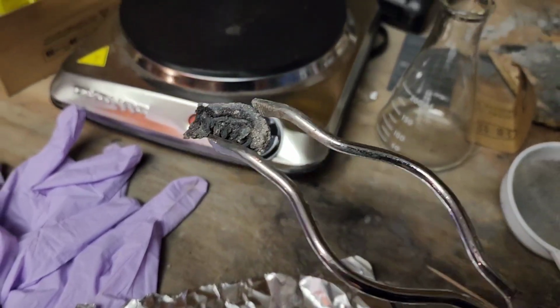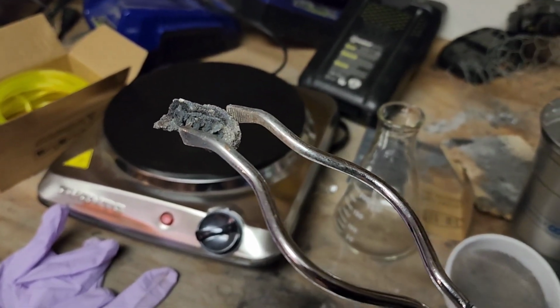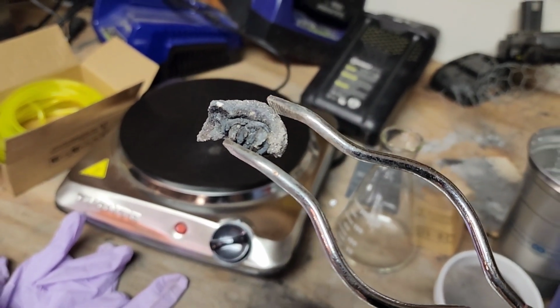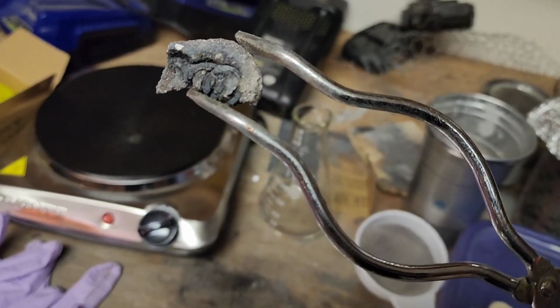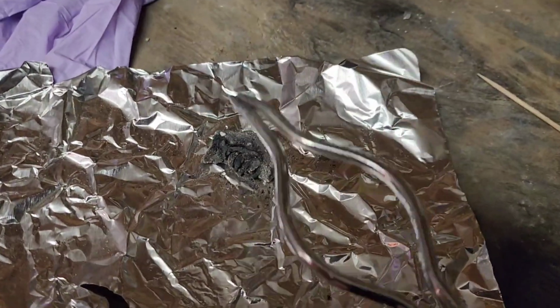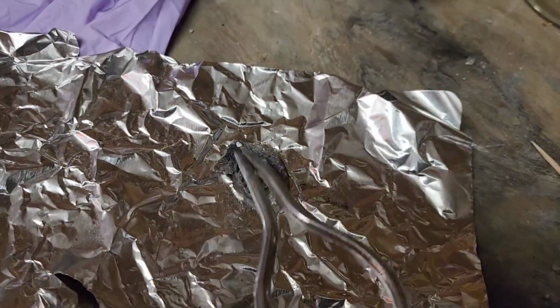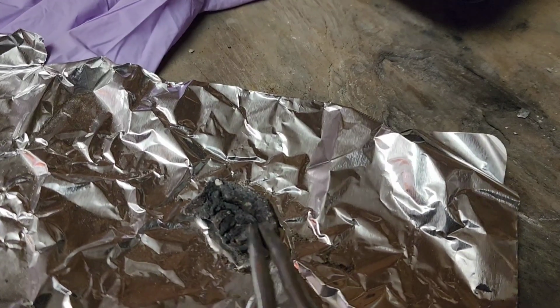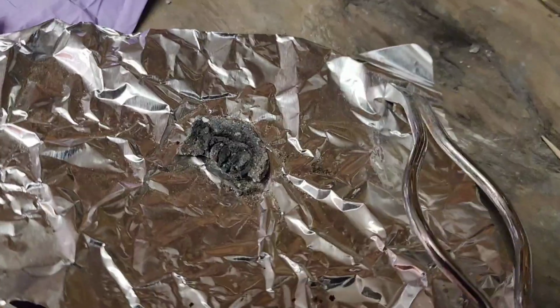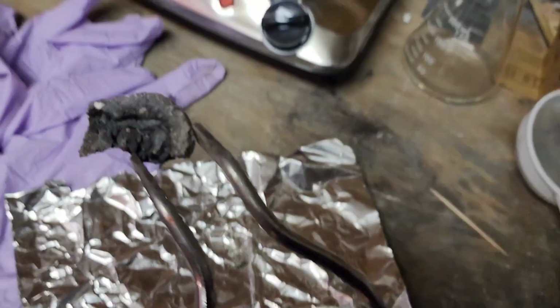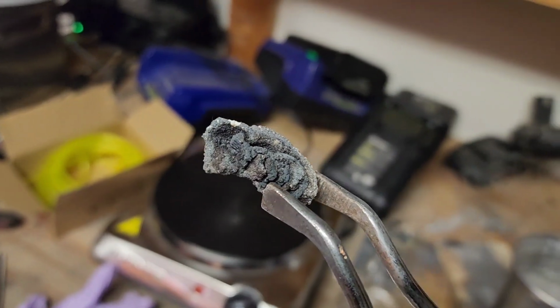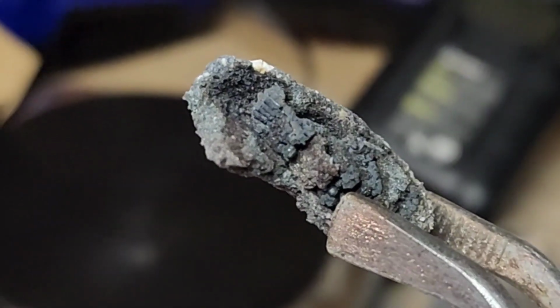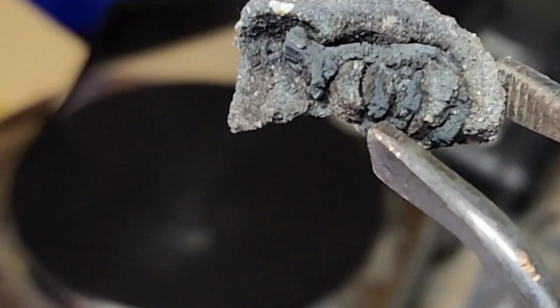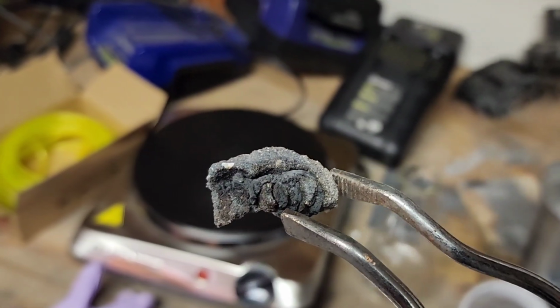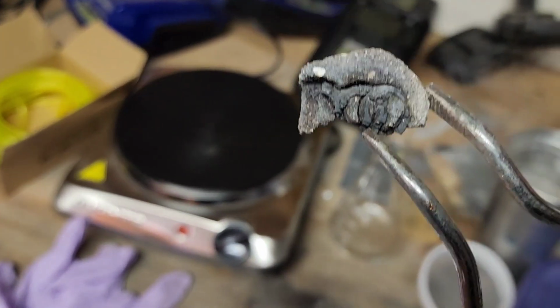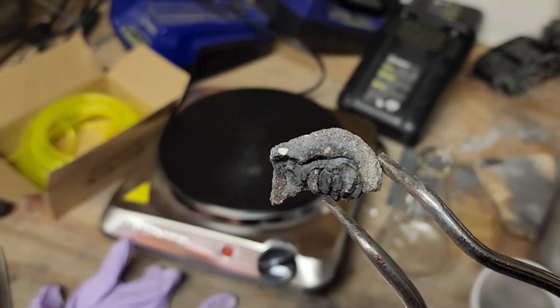The pre-sinter steel, after a little coaxing, was able to be freed from the shell. The pieces in here, the steel components, are sounding kind of hard. The oxidation level on the inside seems to be okay. One thing maybe I could do, I don't think it's necessary, but I could add a carbon layer during the pre-sinter phase. I feel like this resulted in a stronger piece.